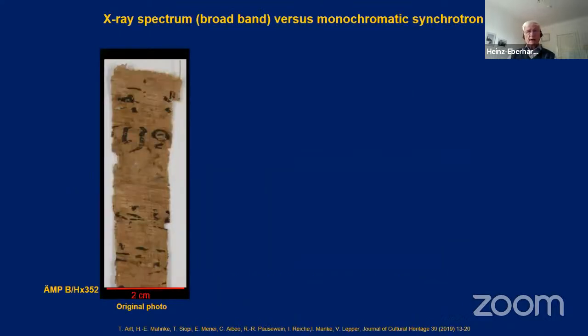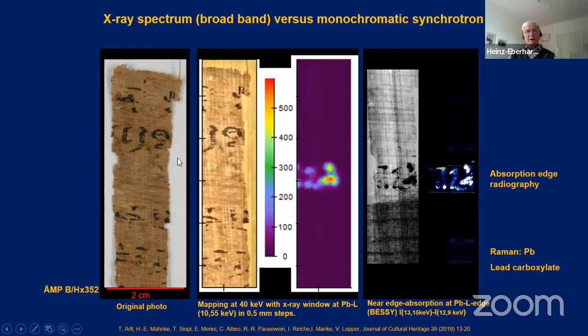Just the final example, and then I guess I am in time. That was a sample which was found in our archive, and you see in this region here, you don't see any writing. You see the black writing here from carbon ink, but nothing here. It turned out that if one does some mapping with our ELIO, setting a window on the lead L lines, that one could easily see a symbol in this area here.